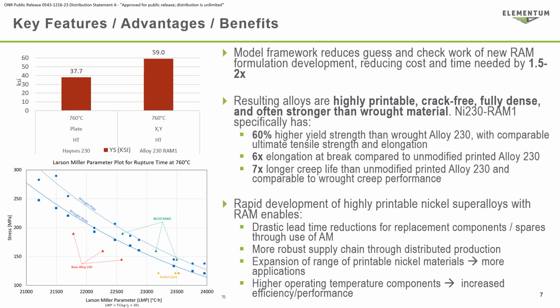This slide summarizes the key features, advantages, and benefits of our approach. It also outlines the advantages of the printed Nickel 230 RAM1 relative to the printed Haynes 230 alone and the wrought plate. With modeling, we estimate that we can reduce the cost and time needed for the RAM formulation development by 1.5 to 2 times. For the Nickel 230 RAM1, experimental validation showed that the material has a 60% higher yield strength than the wrought alloy and a 6 times higher elongation at break than the unmodified Haynes 230 that was cracking. Importantly, we were able to increase the creep life by 7 times relative to the unmodified printed 230 alloy. This is comparable to the wrought creep performance.